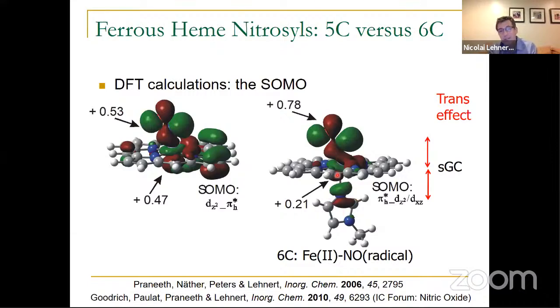That means the iron imidazole bond will become extremely weak, and in the enzyme, soluble guanylate cyclase, it will break, and that induces the conformational change that activates the sensor, then the catalytic domain, to make cyclic GMP. So we can use this exact comparison between these model complexes to understand the electronic effect that leads to the activation of soluble guanylate cyclase by NO binding through this trans effect.